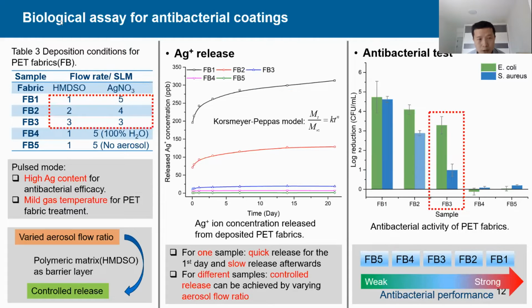Since PET fabrics are widely used in medical applications, we decided to deposit coatings on PET fabrics. For further experiments, we choose pulsed mode to deposit on the PET fabrics for 2 reasons. The first is the high silver content for antibacterial efficiency. The second is the mild gas temperature for PET fabrics to avoid melting problems in the deposition.